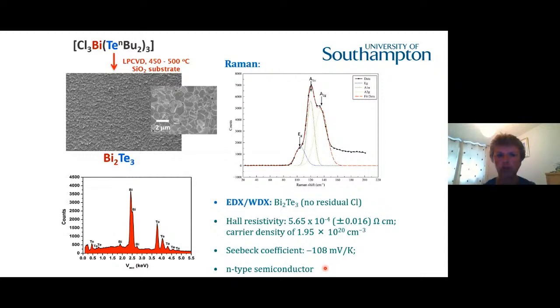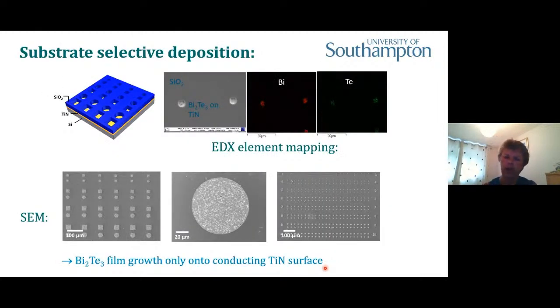We then went on to look at, if we want to make these thermoelectric devices, then we would like to be able to deposit our materials in particular regions on our substrate, on the material that we're depositing onto. And so we've used lithographically patterned substrates, where the blue area is silica, which is an insulating surface. And the yellow areas there are a layer of titanium nitride, which is a conducting surface, which sits at the bottom of this trench, this recess.